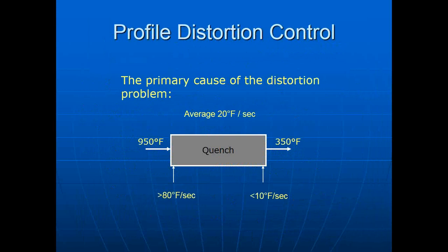So that is the primary cause of distortion. We see the illustration here. If we are averaging 20 degrees per second, then we have a single zone quench where it's only one media throughout the quench, one cooling rate. We're getting excessive cooling at the entry, and we're actually getting inadequate cooling at the exit.